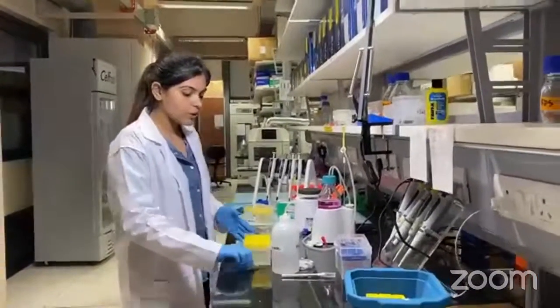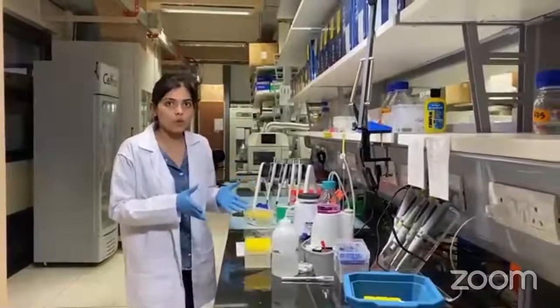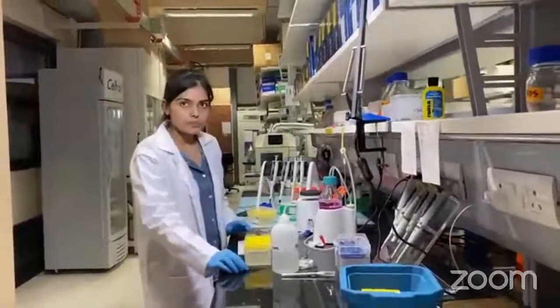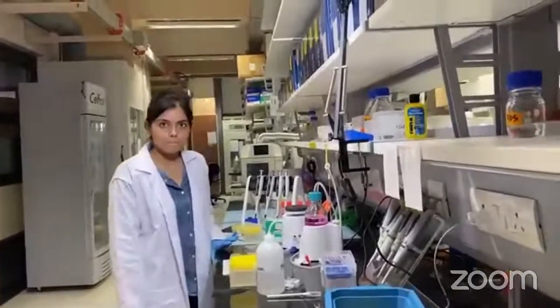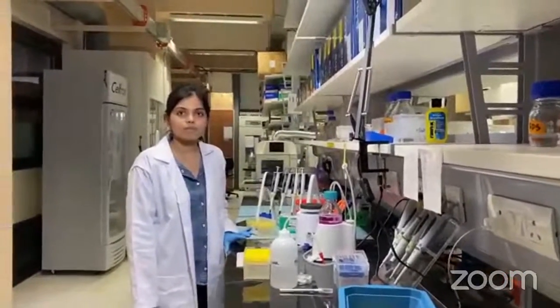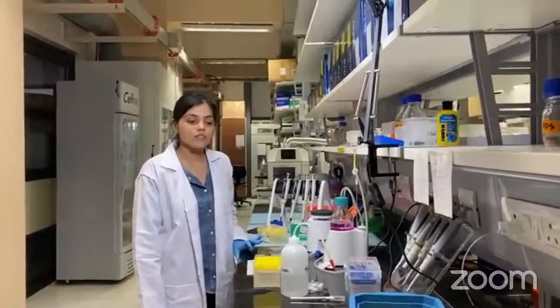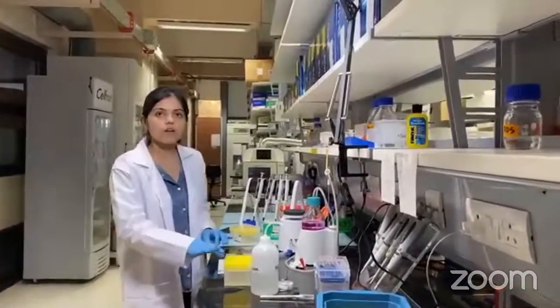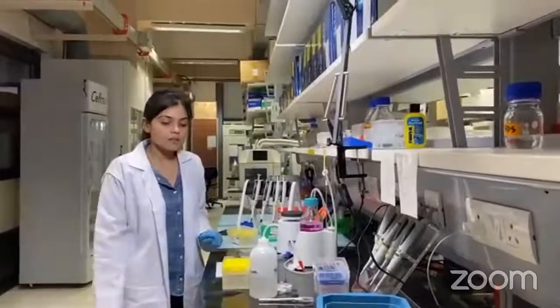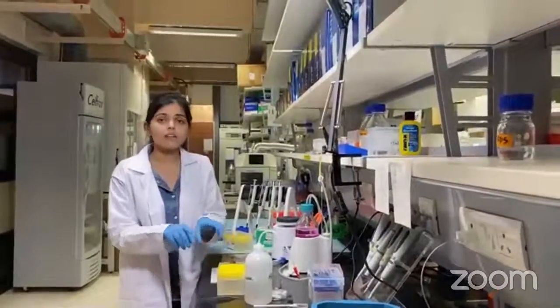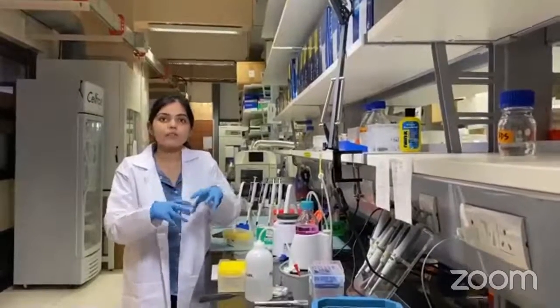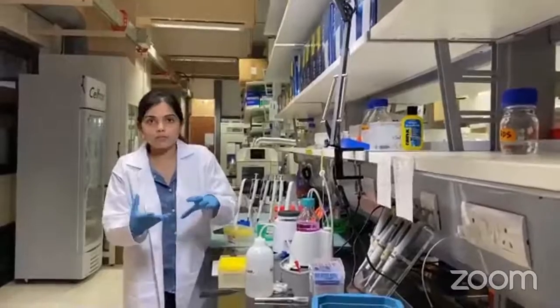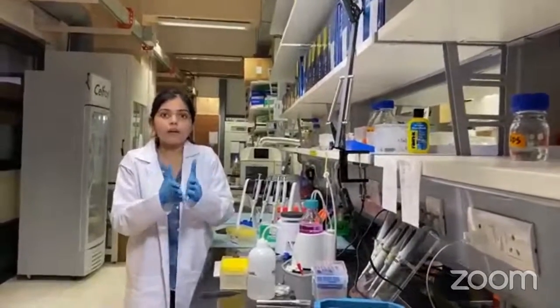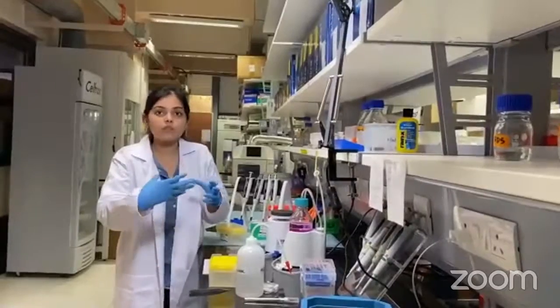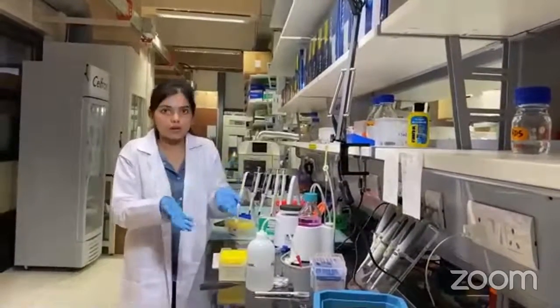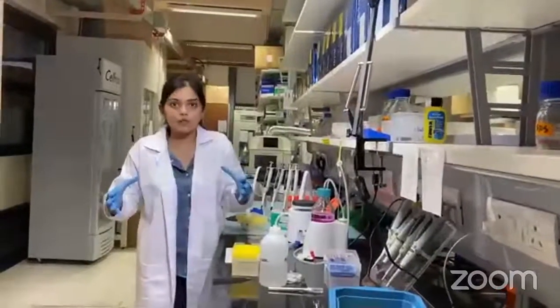Now we are going to homogenize the sample before we add water and expand it. So your cells are already embedded in the polymer mix, right? So what will happen if we just add the water now? They should expand, right? Yeah, so in principle, if I add water to these gels, they should expand. But the problem here is that we have cells in here, and in cells, there are some places which are probably more dense than other places inside the cell, and in that case the expansion will not be even. Some parts will expand faster and more, and some parts will expand slower and probably less, and we don't want that. We want an even expansion of the whole sample.